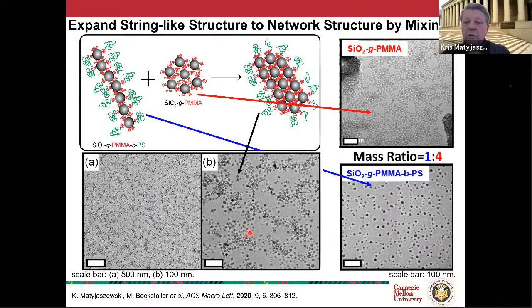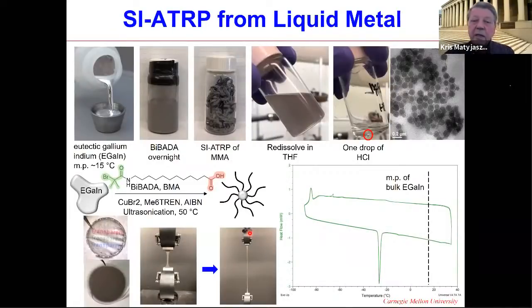So I wanted to show you two more short stories. One is about grafting from liquid metals. Typically we know liquid metals which are based on mercury, but this is very toxic and not a recommended material. But liquid metals have very special applications in soft robotics because of the thermal conductivity, the electrical conductivity, and elastic properties. One of these examples is eutectic gallium-indium alloy, which has a melting temperature around 15 degrees. So at room temperature, it is a liquid.